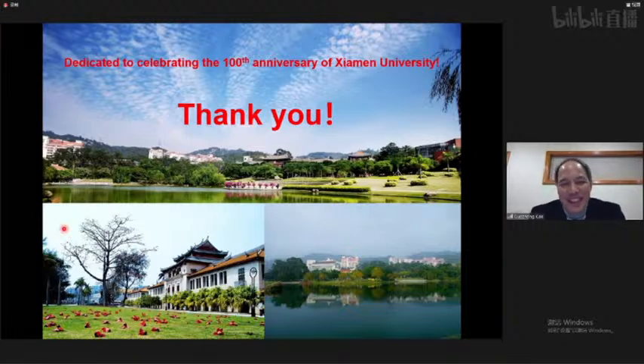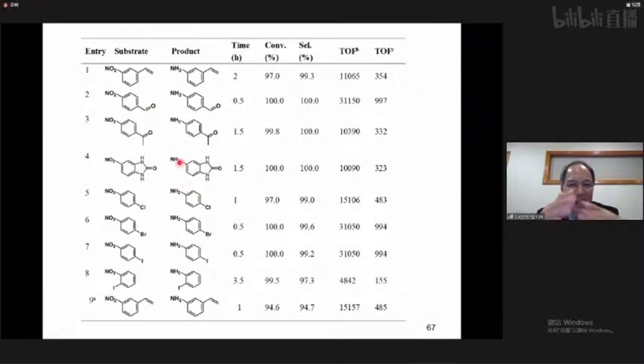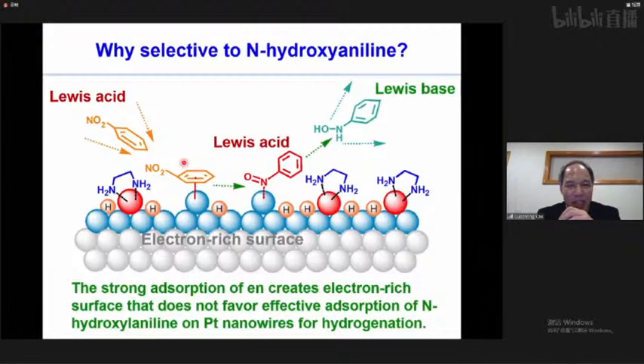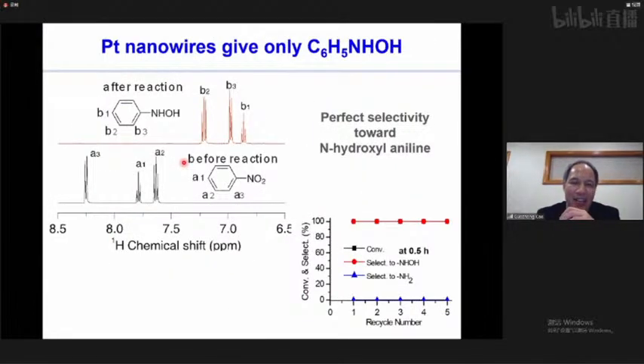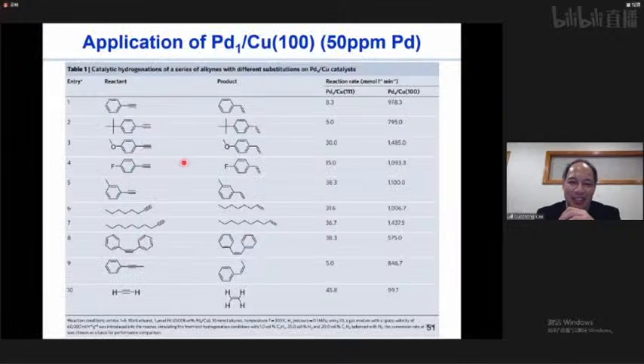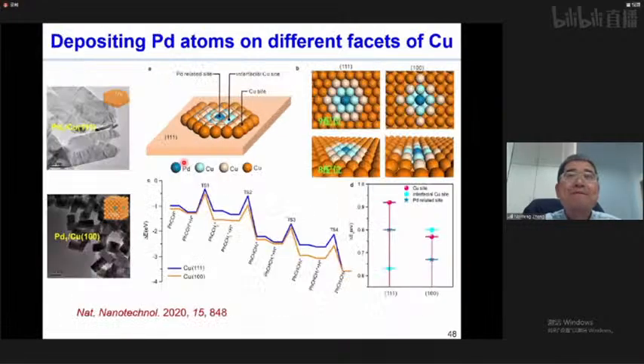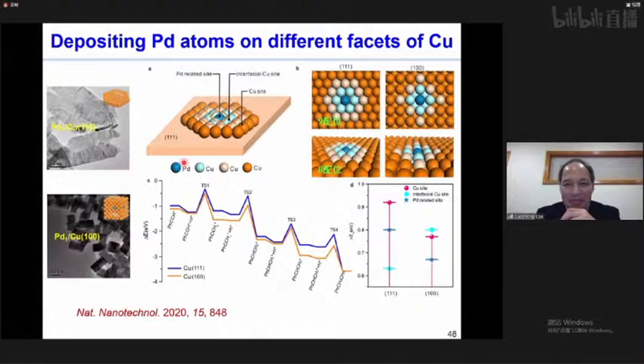When you talk about depositing palladium on copper, when you deposit on the copper 100 surface compared with the 111 surface, the 100 surface gives you much higher catalytic activities. Although they both form hexagonal packing, or not exactly. Now, what is exactly the reason they get a much higher activity?